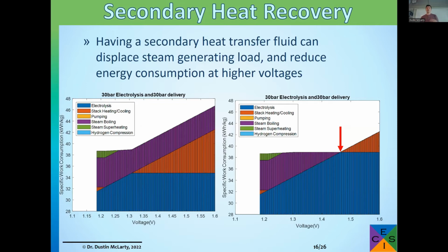Right. If you did have that secondary heat transfer fluid in your stack and you were able to move the heat from the stack to actually displace some of that preheating, that has a distinct advantage for you. You can operate at a much higher voltage, meaning more power, more current density, for the same net energy consumption. Because really it's taking some of this red heat that's recoverable from the stack and displacing here this purple section, which is your steam preheating. So you get this wide operating window that is effectively the same efficiency for your hydrogen production. And so that can have a lot of advantages.